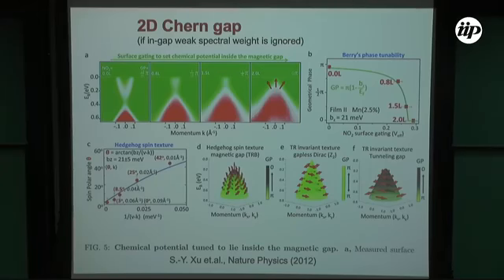And then we can see that as you move out in energy, far away in energy, your spin texture is similar to the undoped topological insulator. So in other words, if you place your chemical potential here, spectroscopically it will look like there is a pi Berry phase. But if you're up here, then the pi Berry phase is destroyed. So there's a Berry phase tunability that you can achieve by changing the chemical potential, at least spectroscopically. So this is a signature of a Chern gap insulator. It's a characteristic thing of the Haldane model.